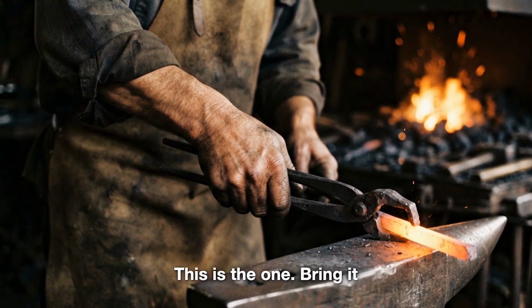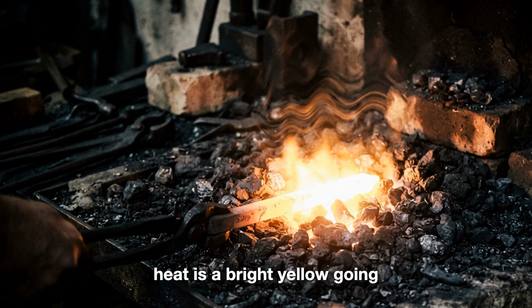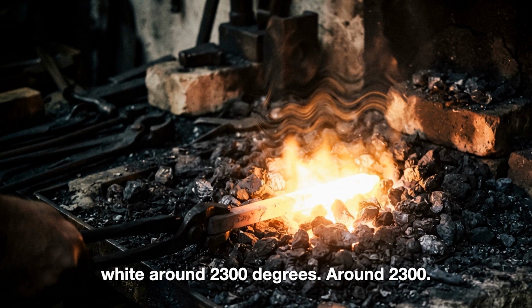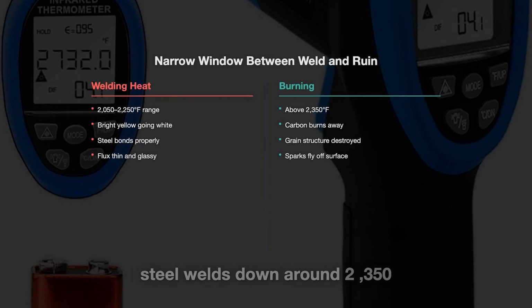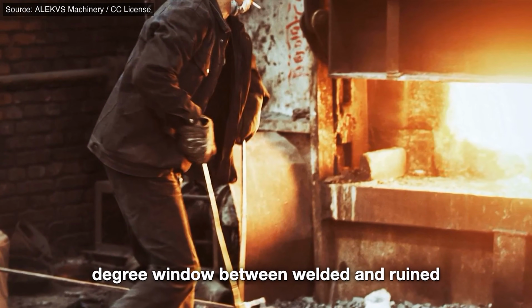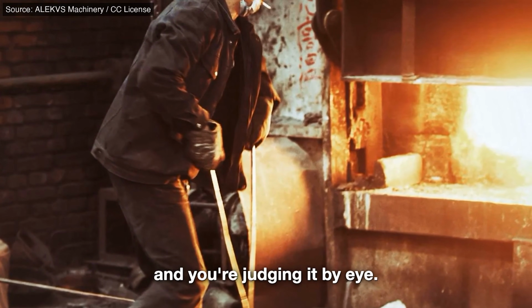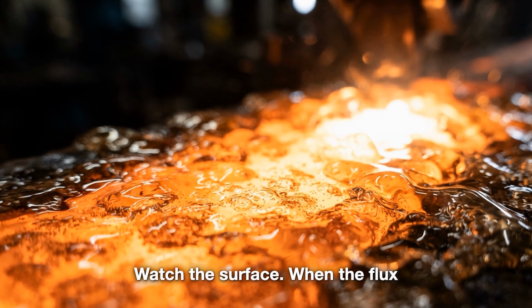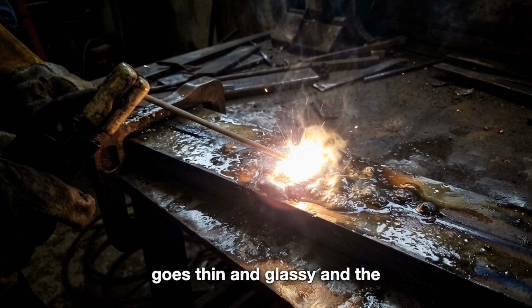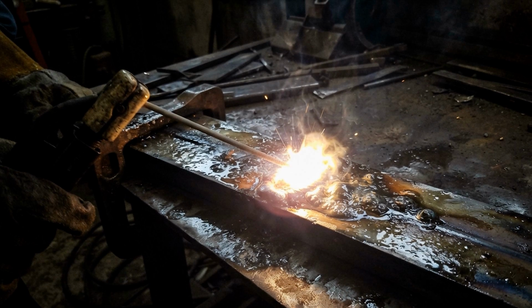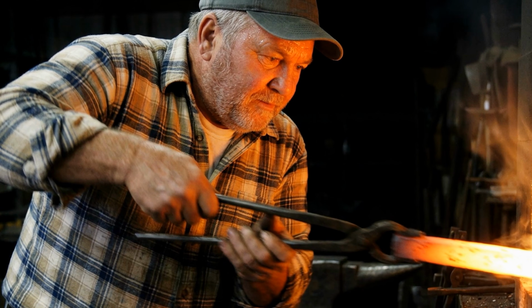Step 6. This is the one. Bring it up to welding heat, and welding heat is a bright yellow going white, around 2,300 degrees. But here's the trouble. High carbon steel welds down around 2,250, and it starts to burn just above that. Plain 1084 burns at 2,350. You have got about a 100-degree window between welded and ruined, and you're judging it by eye. So here's how you read it. Watch the surface. When the flux goes thin and glassy and the bar looks wet, like it's sweating, that's your moment. Out it comes, out when it sweats.